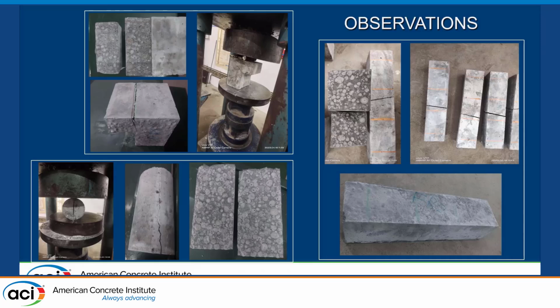On the right, you can see the shear strength and flexural strength test. In that also, the first sample is the sample without fiber. It breaks from the center. The second sample shows the fiber reinforced concrete, which doesn't break fully, imparting ductility and tensile properties, which was our major objective for the samples.